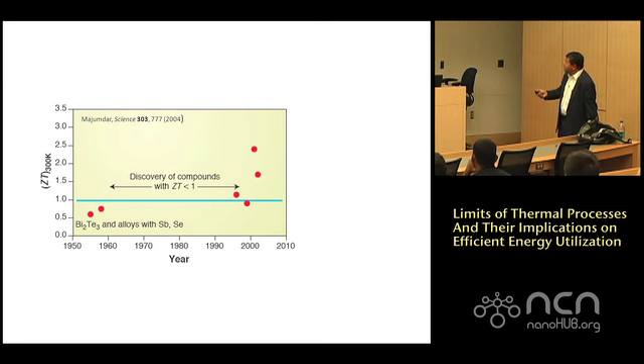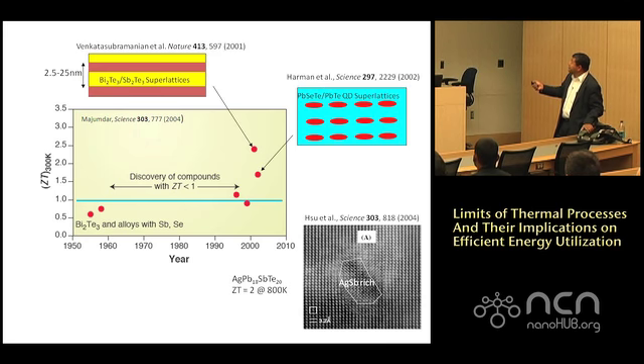And Millie Dresselhaus's work showed that maybe nanostructures have a way. What they said was that the S squared sigma, the power factor, the numerator of ZT, could be improved, and thereby you get in. And people started making nanostructures. These were the nanostructures that were made. This is Rama Venkatasubramanian's group, Ted Harman's group. This turned out to be actually not correct later on. But nevertheless, they showed that you can get to higher ZTs.